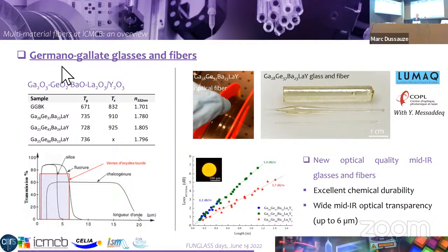So here is the matrix that is the starting point: gallium, germanium, barium, oxide. And then after looking for several combinations of doping elements, we found that modifying the matrix with rare earths like lanthanum or yttrium helps draw the materials into fibers without losing the extension of the window in the infrared, and without reducing the mechanical properties of the fibers. So here is an example of a study that was conducted with the team of the COPL in Canada. Really a collaboration with the team, which is still going on on these systems.